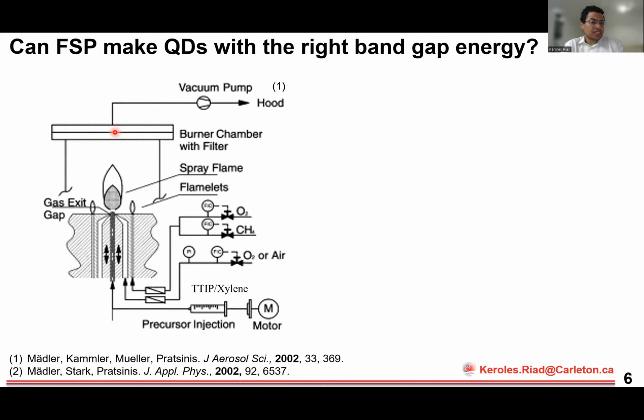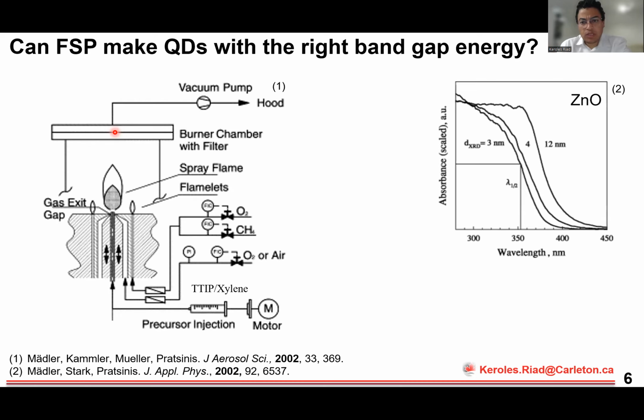So the question that I had at this point is, can FSP make quantum dots with the right band gap energy for my application? Before this, there was only one paper that had made quantum dots with FSP, and that's Professor Madler's work making zinc oxide quantum dots. As you see in this graph, he made zinc oxide particles of 12 nanometer, 4 nanometer, and 3 nanometer in crystal size.